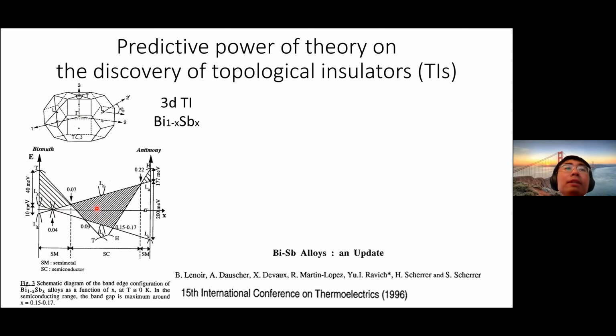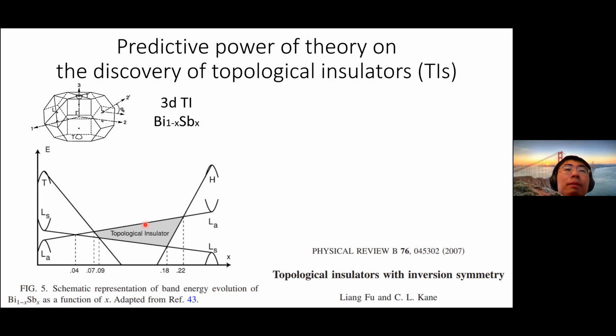So just based on this simple picture of band crossing, theory immediately predicted that there's going to be a region in this parameter space, depending on the doping, in bismuth antimony, where you end up with a topological insulator. And that's what theory discovered.